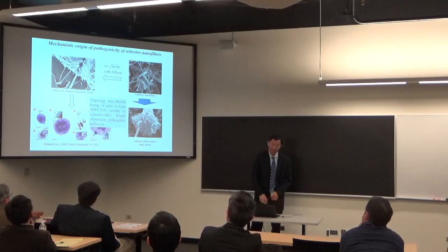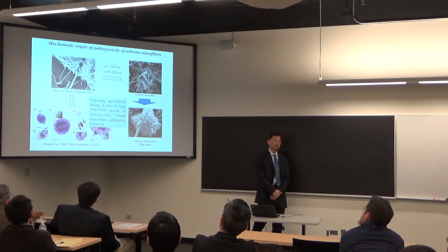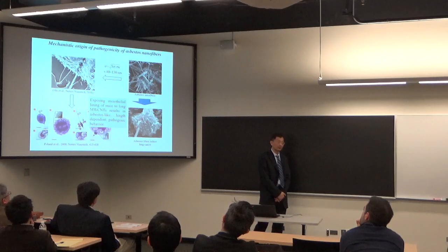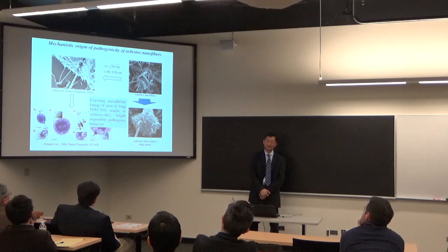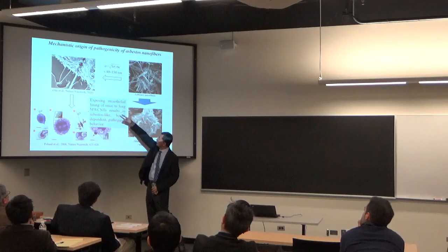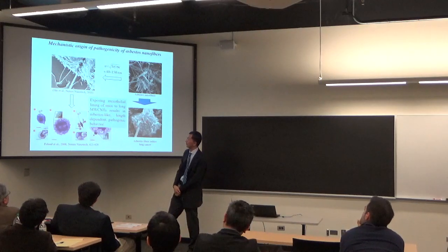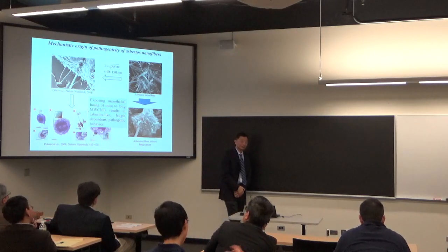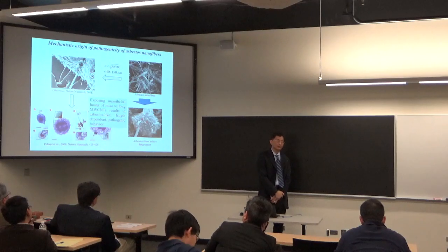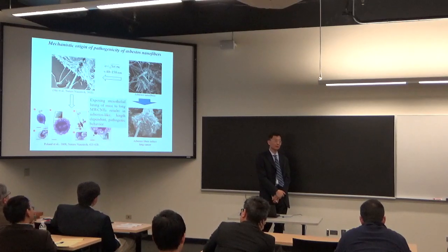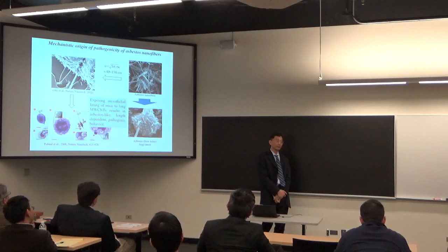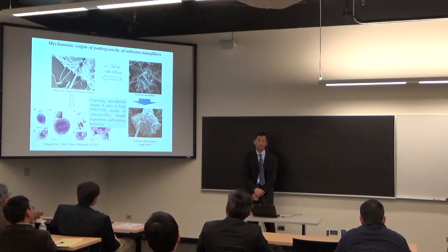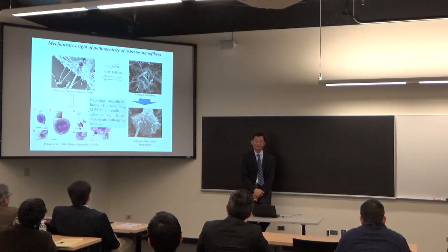So actually, not surprisingly, when people study cell interaction with carbon nanotubes, they see exactly asbestos-like disease, right? They see mesothelioma, injection into the lining of mice of long carbon nanotubes results in asbestos-like length-dependent pathogenic behavior. So this asbestos problem, this cancer problem, the original cause is not chemistry. It's not because of the chemical composition of the material. It's a mechanical problem. Okay? It's just a geometry problem, actually, the origin of this.